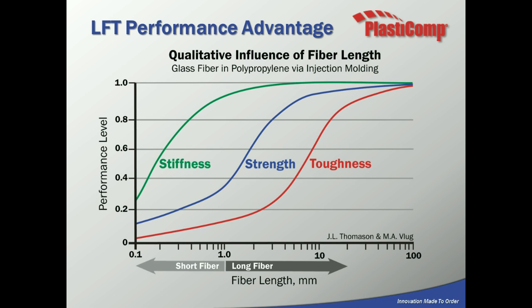So here's a graphical representation of what we've been just talking about. Over on the left, we have a performance level, and on the bottom, we have fiber length. And as you can see, as you move to the right, we get longer in the fiber length. As you start off on the side with the stiffness, you can see that stiffness goes up fairly quickly no matter what fiber length you start with. As we move towards the right and we get over 1 millimeter in fiber length and then beyond, we start to see increases in strength.